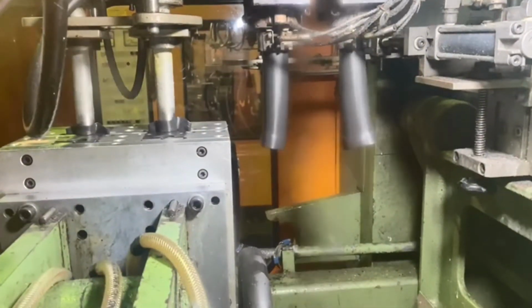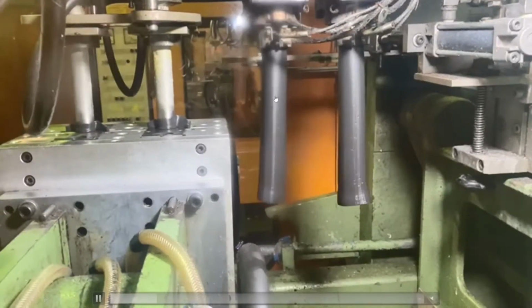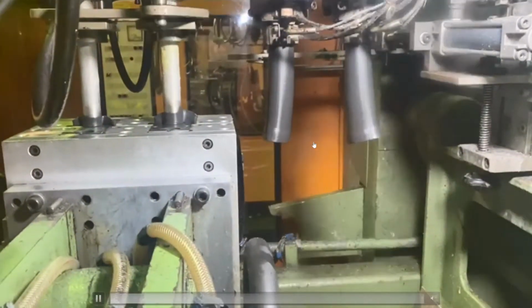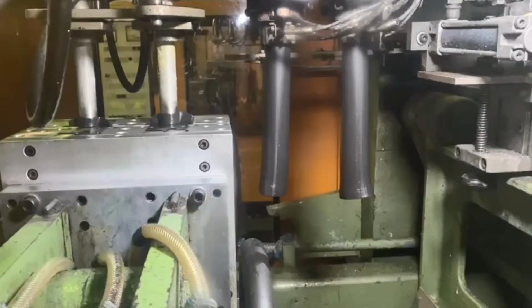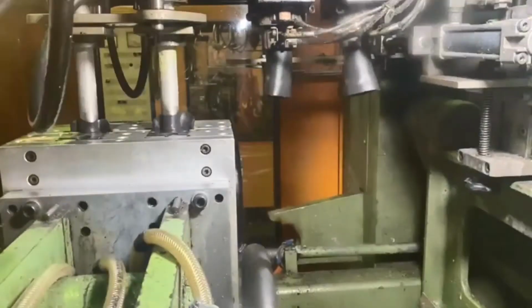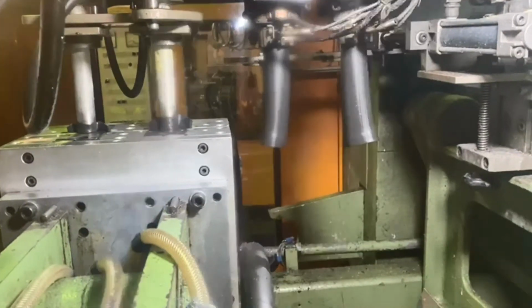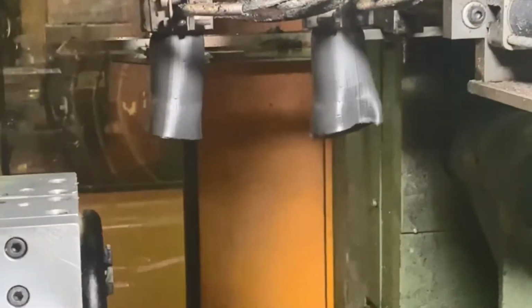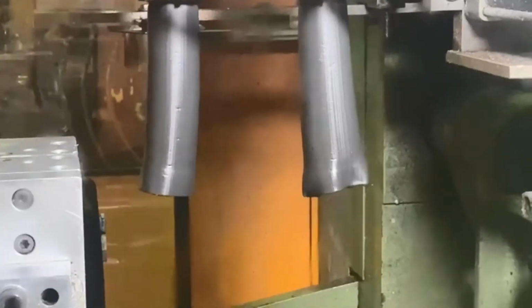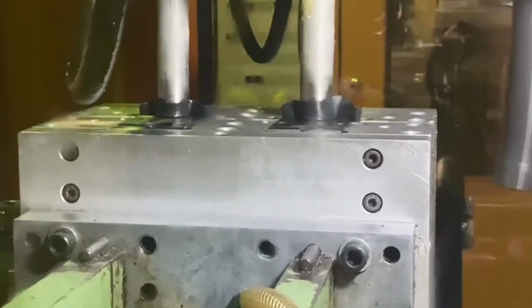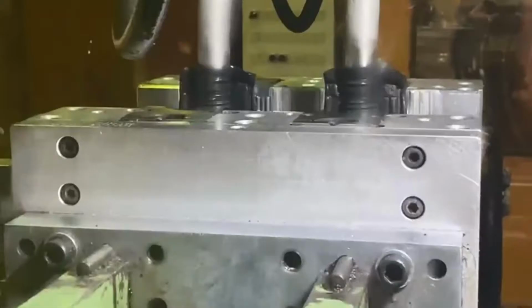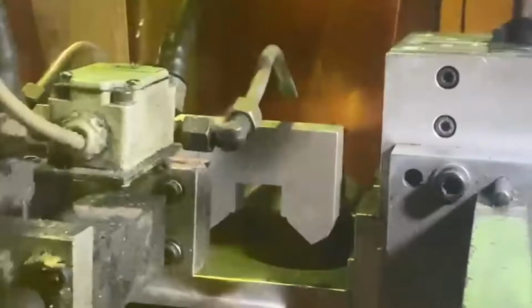So what you're looking at here is our plastic, 100% PCR, being extruded through an extrusion blow molding line. Normally what you would see with a mixed source feedstock like ours is these tubes descending at different rates or collapsing. But the additive, through the way it works, allows us, under these temperature and pressure conditions, to flow the material at exactly the same rate, at exactly the rate that we tell it to flow at. And this is quite unique in that typical melt flow control solutions have involved chemically altering the bonds inside the plastic, whereas we describe our additive as a rheologically dynamic additive. It's actually completely passive unless it's under certain shear and temperature conditions.